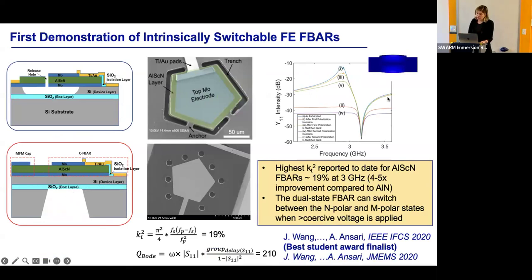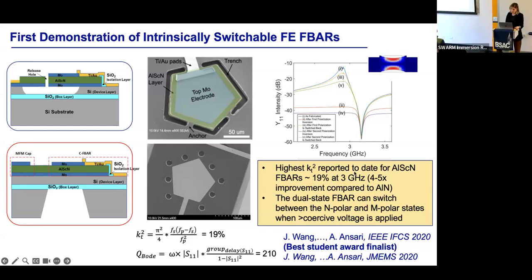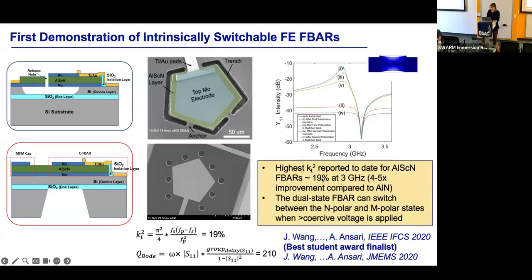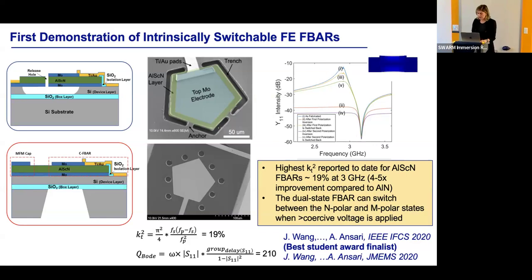And we were able to show that you can tune the polarization of your FBAR and effectively turn it on and off by playing with the DC voltage that you apply to the AlScN layer. And this work also reported the highest kt² for FBARs, about 19%, which again just means that this enables wider bandwidth filters, and that's something that a filter designer would really like to have.